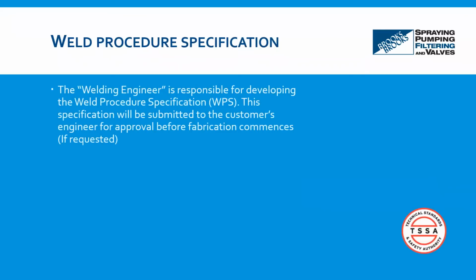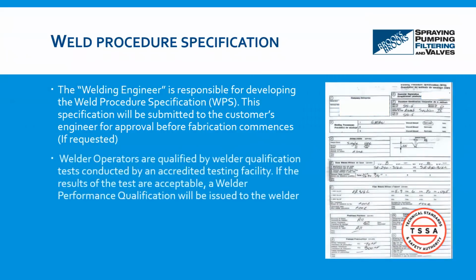So the weld procedure specification, how do we get it? Under this, there is also a procedure qualification record that needs to be qualified, and it's acquired under the guidance of both the shop manager and QA manager. First, the welder would have to weld the test coupon. Here we have an example of a weld procedure specification. Let's just use stainless steel to stainless steel as an example. Once the welder uses the weld process of interest and completes the welding of the test coupon, that test coupon is then sent to an accredited testing facility who would test it for both chemical and mechanical properties to ensure that it's within spec and code. Once that's done, it's sent to the technical authority who would then grant the approval and authorize the shop to use that weld procedure.